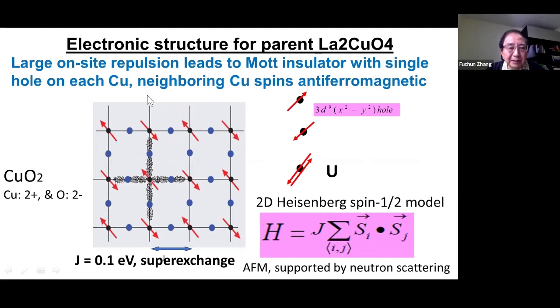And this is a picture for the parent compound, like lanthanum 2 copper O4. At each site, we have just this copper 3d x squared minus y squared orbital, which is singly occupied, while the other orbitals on the d are completely occupied. So I use a hole notation: just one d hole at every site. The reason the system does not like two holes on the same site is Coulomb interaction. The Coulomb interaction repels them, which forbids double occupancy of the two holes.